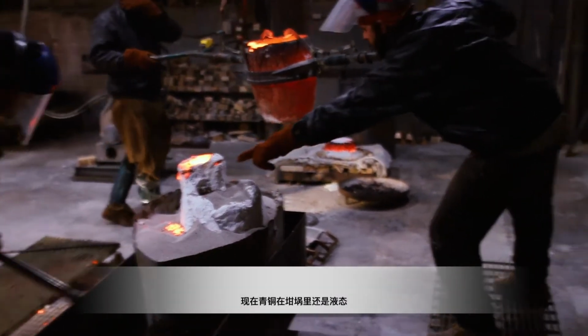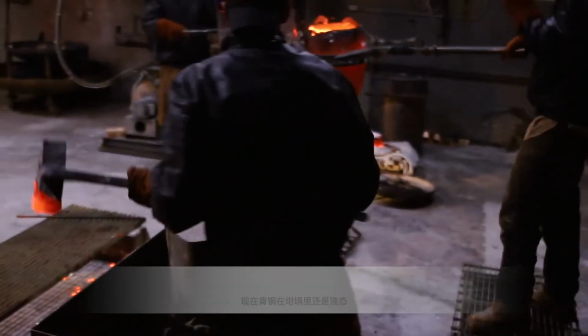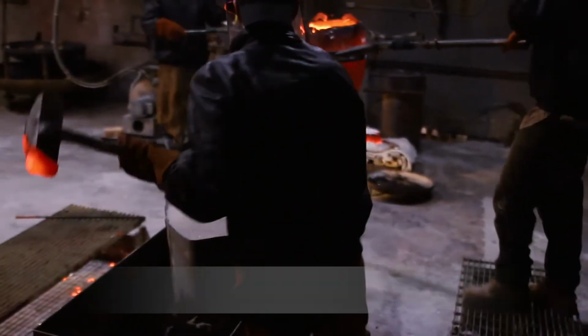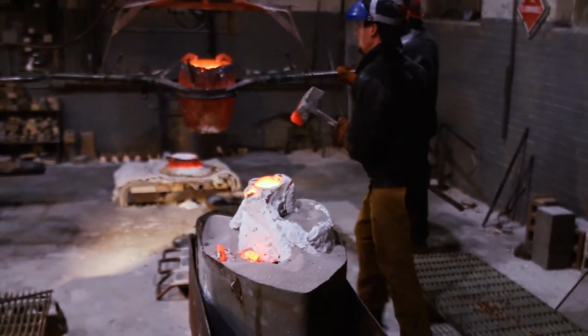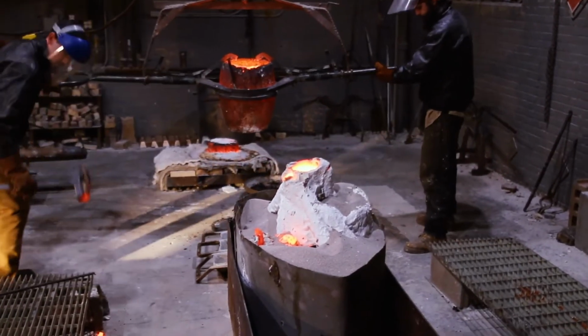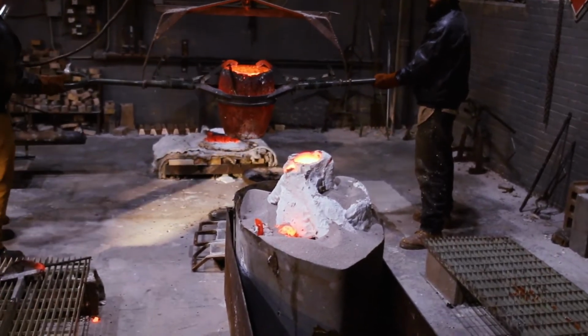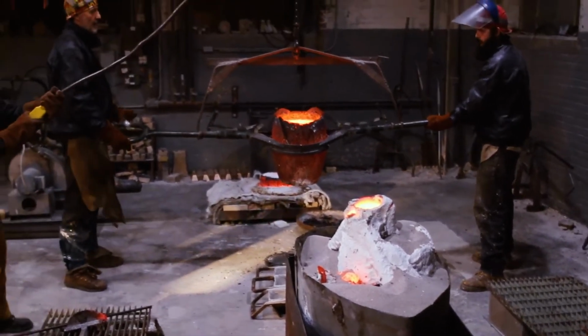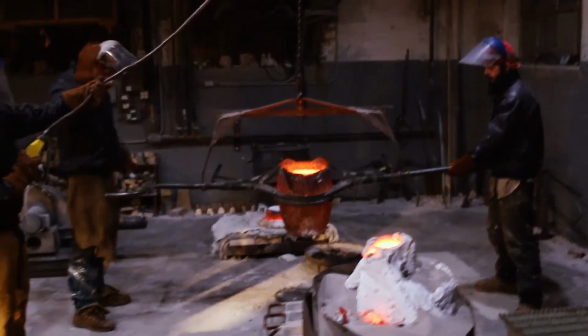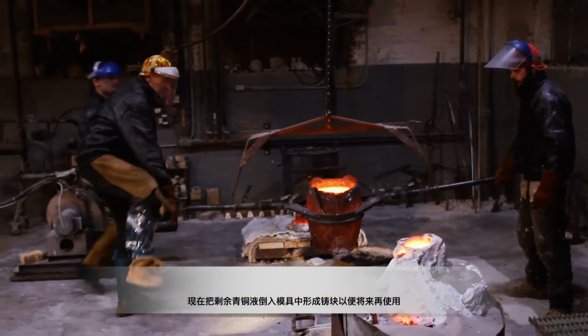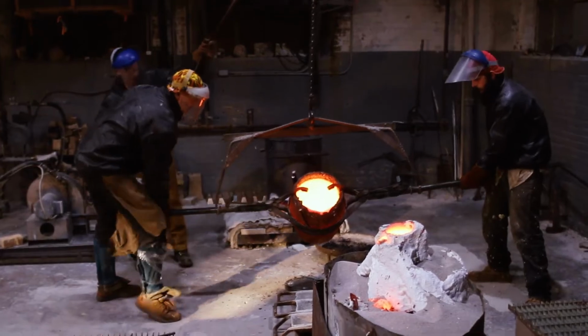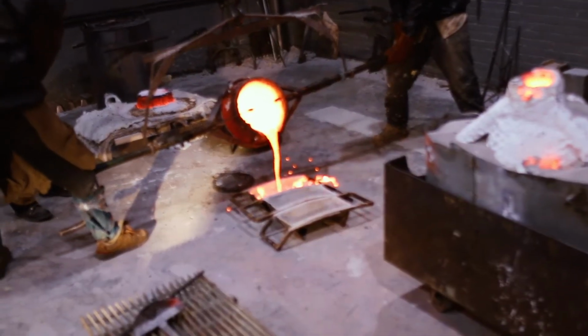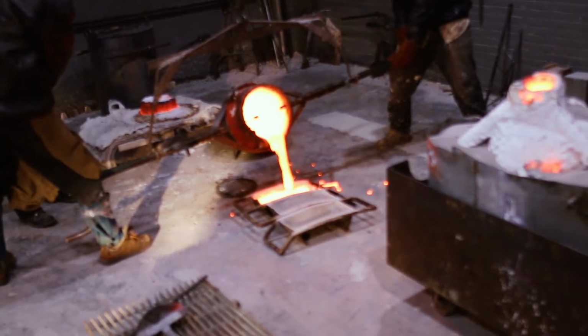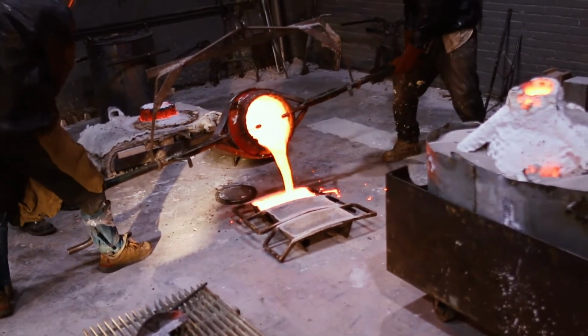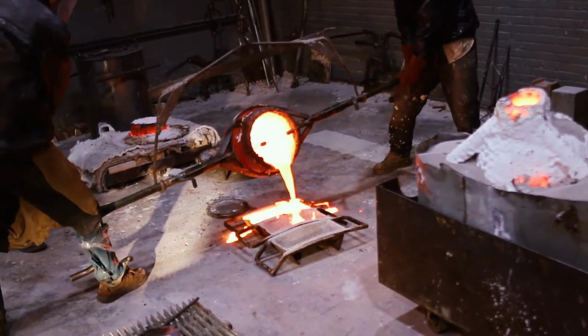And although the metal's still liquid in the crucible, by now the metal is solidifying in the 1/4 inch space that was left from the burning out of the 1/4 inch wax. Because the thinnest areas solidify first, and then the thicker areas, and then the thicker, and so the top of the pour spout's still liquid. But inside the mold might not even be glowing anymore. It might already be darkened.